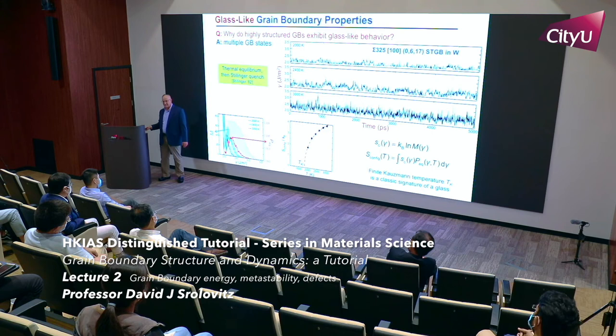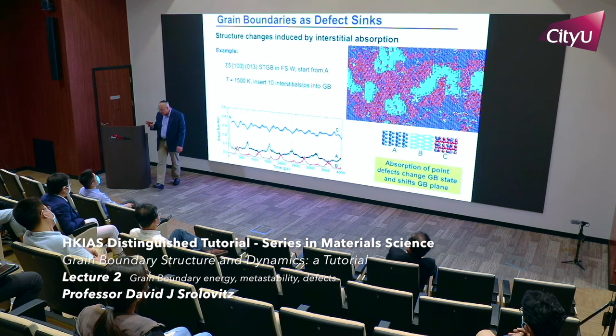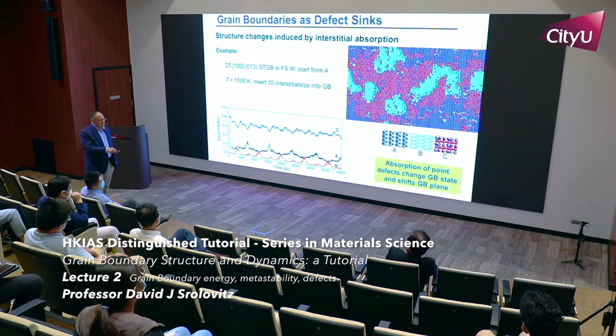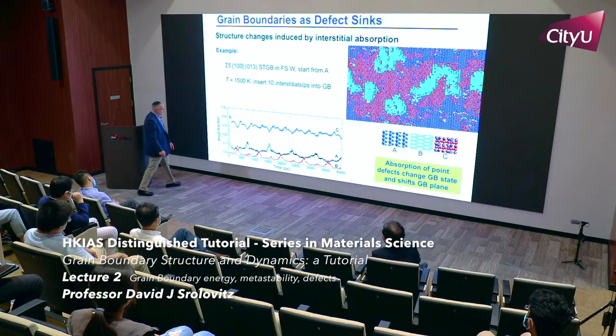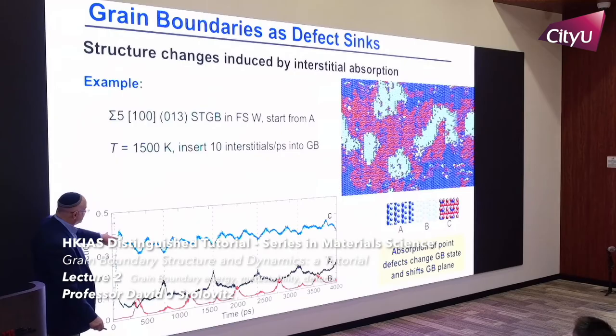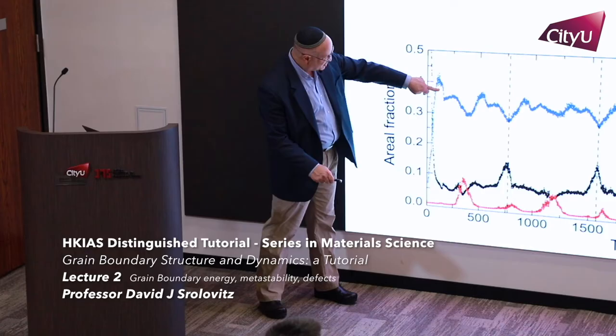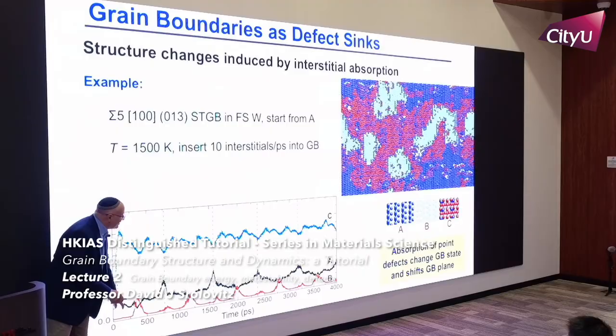Another example: take a grain boundary, equilibrate it at 2000, 2400, or 3000 K, quench to zero temperature, measure the energy, repeat. At 3000 K the fluctuations are much larger. This gives a distribution of accessible states. Plotting configurational entropy versus temperature, the curve extrapolates to zero at a finite temperature — the Kauzmann temperature. The entropy going to zero at a finite temperature violates the third law of thermodynamics in the usual sense, but this is exactly what glasses do. This is the Kauzmann paradox, typical of glass-forming systems. Finally, adding interstitials to a boundary in configuration A produces structures A, B, and C, and as a function of time the dominance of different structures oscillates periodically.